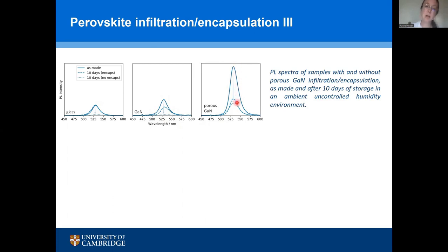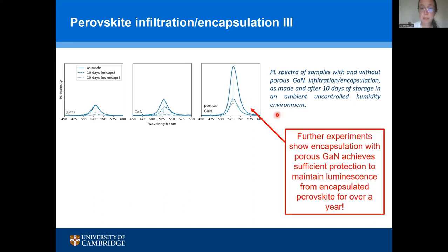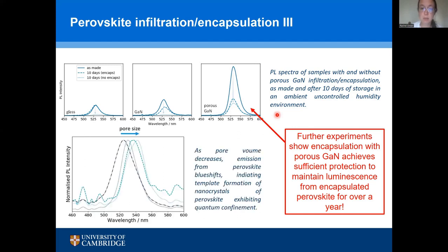But if we have material that's encapsulated in our porous GaN, although we do see some degradation, actually the degradation is only the same as it would be if we'd properly encapsulated it as soon as it was grown in a little glass box and never exposed it to ambient. It doesn't degrade very much at all. And in fact, we left these samples for a year and found that they were still showing perovskite luminescence over the course of a year, which is almost unheard of for these types of lead halide perovskites.